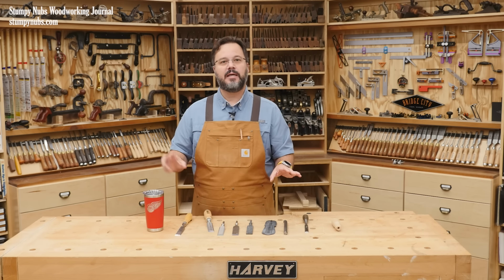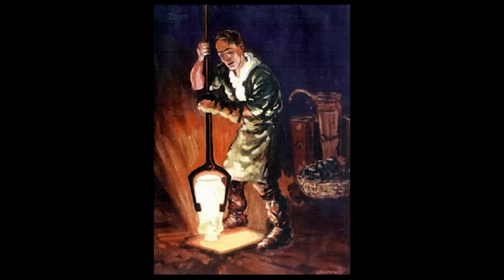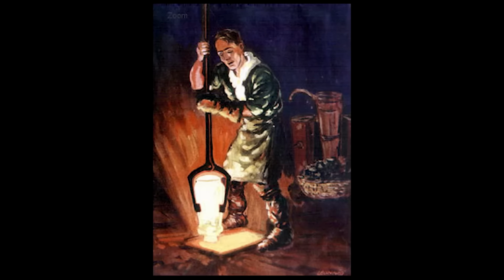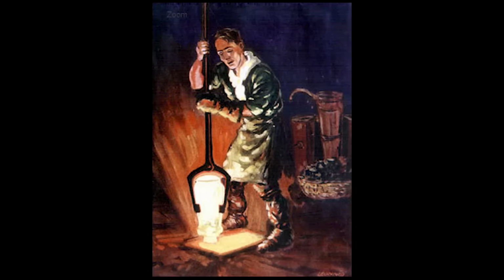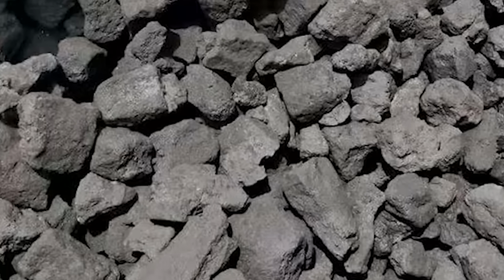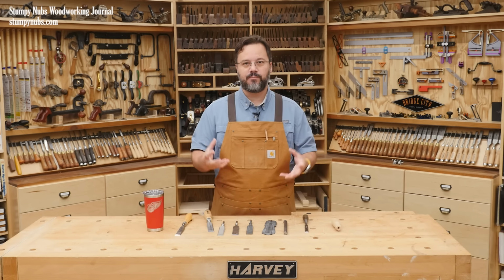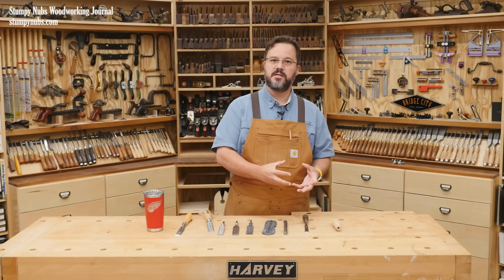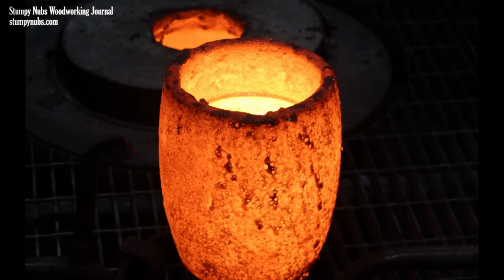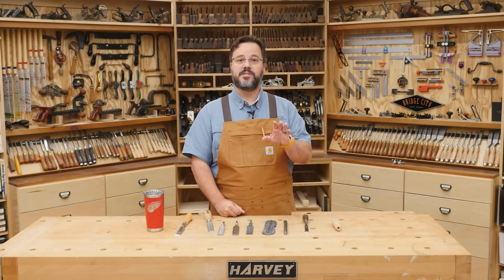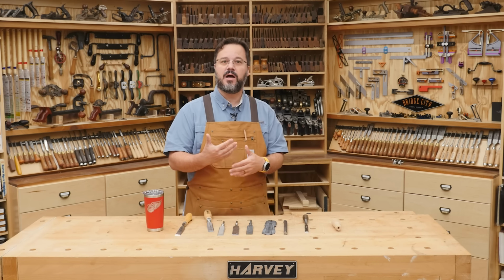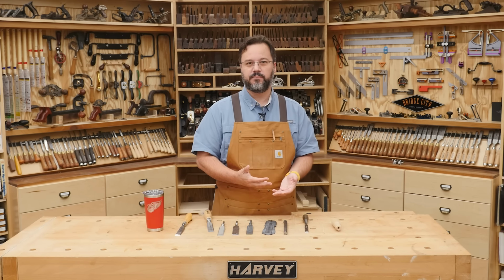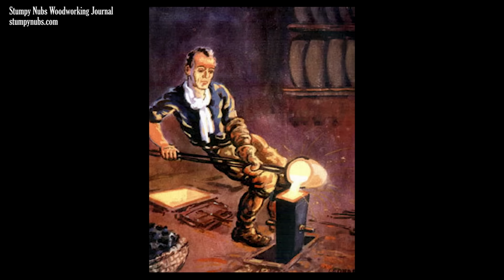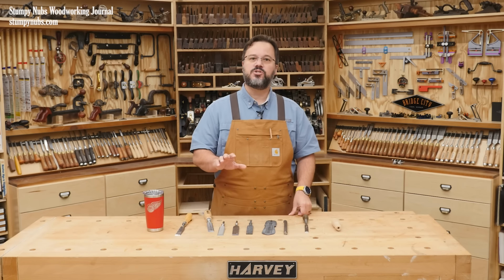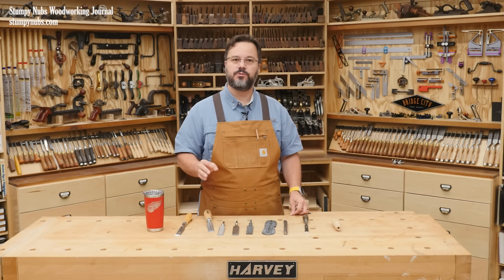but perhaps the most important improvement in Western tool steel came back in the 1700s when a watchmaker who was just looking for better spring material came up with the process of using coke rather than coal to create extreme temperatures and melt blister steel in a sealed container called a crucible. By melting it, it was able to amalgamate the carbon in the iron in a much more consistent way. The molten steel was then poured into molds to make ingots, which could then be forged and shaped into tools. This was called cast steel or crucible steel.